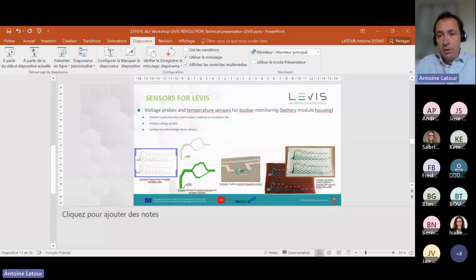Actually, so you can see some examples. We have large equipment, so we can print on larger substrates, something like 50 by 30 centimeters. You can see here conductive lines plus an insulating layer on top of that that are going to be processed during the bus bar fabrication.